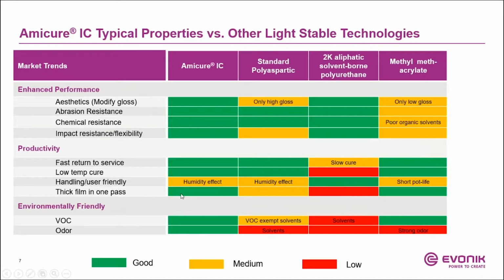Thick film in one pass is important. Again, that's important in terms of productivity, because you don't want to put multiple layers down. You don't want to keep applying multi-coats to build that coat. So you can get up to very thick coating in one pass with polycarbamide technology. That's why I have green, and same with MMA. Standard polyaspartic and polyurethanes, again, they use solvent in their formulation, so that limits how thick you can apply in terms of your film thickness.